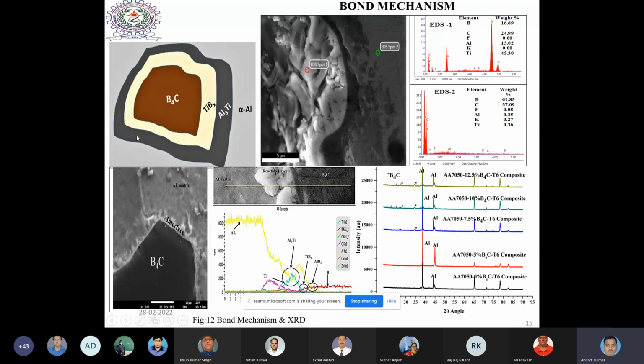I have tried to show this reaction layer like this. There is a B4C particle at the center, and in the vicinity of B4C there will be a layer of TiB2 or TiB, titanium boride. Since titanium is the major reacting element, it increases the local temperature near that B4C particle, which melts and reacts with the matrix, and it will form TiB2, then Al3Ti, and then alpha aluminum. If this kind of reaction happens, only then can we be sure that our composite has been formed. So I was able to achieve this kind of reaction.